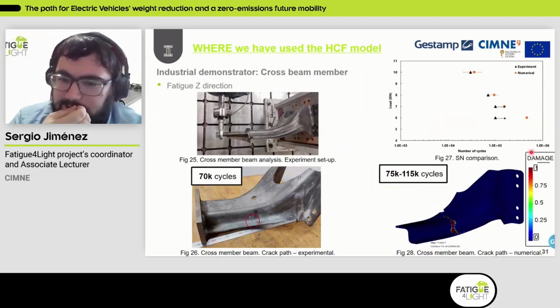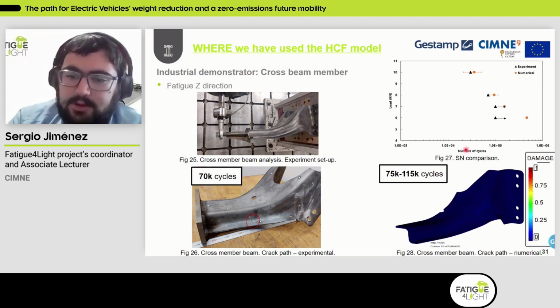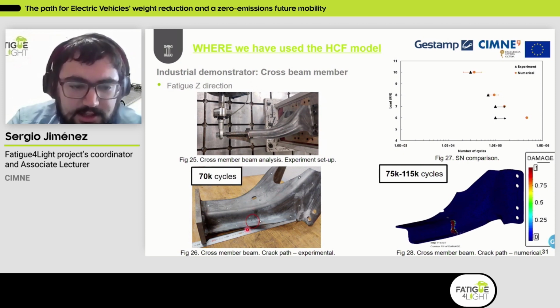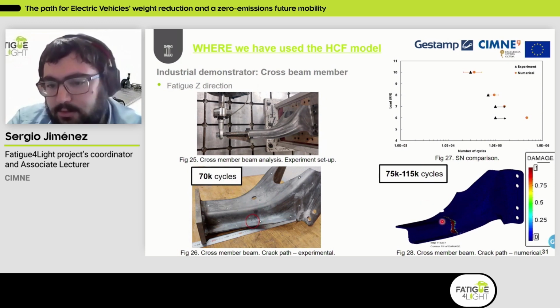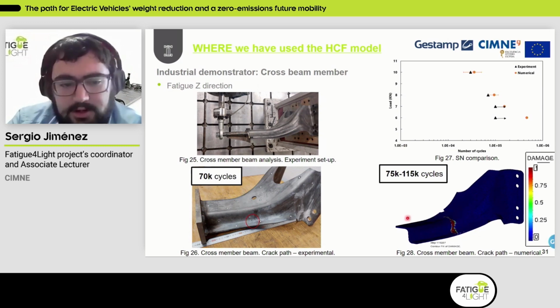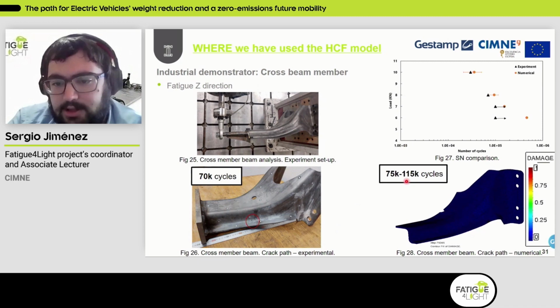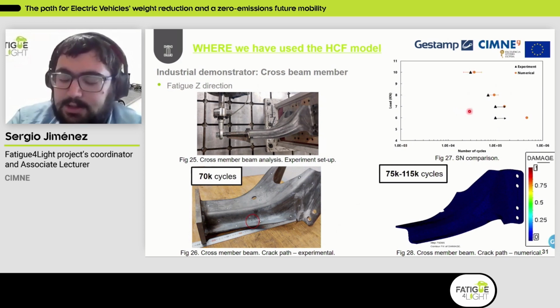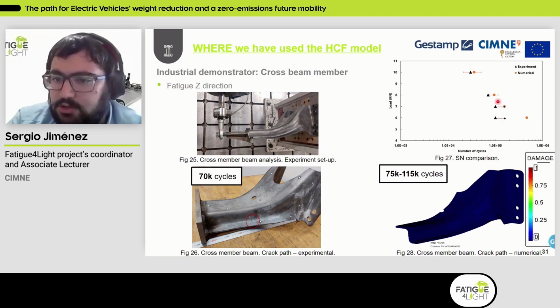And then here we have the results obtained for these fatigue loading conditions. So basically this is the one corresponding to the Z loading direction, where experimentally they detect this crack appearing in this region after 70,000 cycles. And here we have the crack more or less in the same region, and this is the type of propagation that we were obtaining for this particular scenario. And here you can see the correlation for several loads being applied to the crossbeam member. Just to mention that these two correspond to runouts of the experiment.